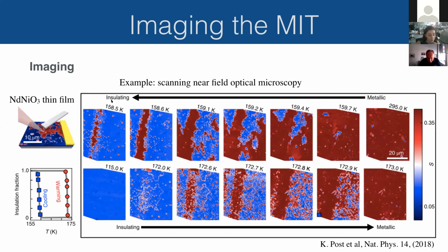Okay, something that is really nice is, at least for neodymium nickelate that has this clear hysteresis loop, you can clearly see that it's first order also by looking for phase separation. So here is an example. This is scanning near field optical microscopy, which is just an indirect measure of the conductivity of the material with spatial resolution down to tens of nanometers. So when you start at high temperature, the material is a metal. And as you cool down, you get nucleation of insulating phases until finally, below the transition temperature, everything is insulating. And similarly, when you warm up, you get nucleation of the metallic phase again, until finally at high temperature, everything is metallic. So this is a really beautiful first order transition.